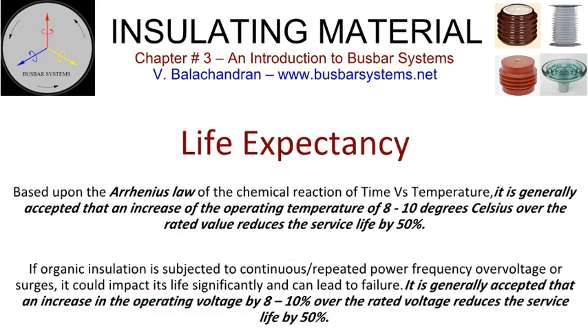Expected life, organic insulations. An insulator made of organic material will decay and has a definite life. The life of organic insulating material is around 20 to 25 years. Any thermal overload reduces its life. Arrhenius law. It is generally accepted that an increase of the operating temperature of 8 to 10 degrees Celsius over the rated value reduces the service life by 50%. Similarly, an insulation system is designed for an operating voltage. If organic insulation is subjected to continuous, repeated power frequency overvoltage or surges, it could impact its life significantly and can lead to failure. It is generally accepted that an increase in the operating voltage by 8 to 10% over the rated voltage reduces the service life by 50%.